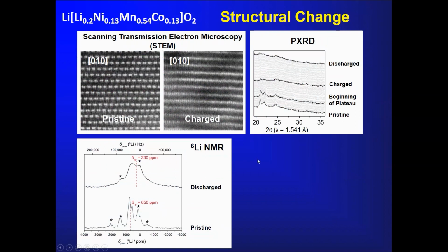Now, what happens when you charge a cell with this material? So let's first of all look at some scanning transmission electron microscopy of the particles on doing so. So first of all, this is a STEM image, again looking along the layers, along the 010 direction, before charging. And these dumbbells, the light features here, of course, are the heavy scatterers, the transition metal ions in STEM. So these dumbbell arrangements that you see are very characteristic of what the honeycomb structure looks like when you're looking along the layers.